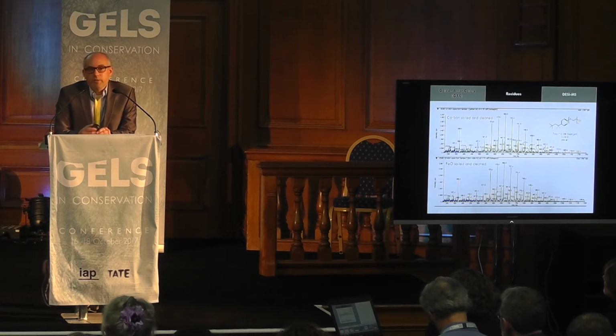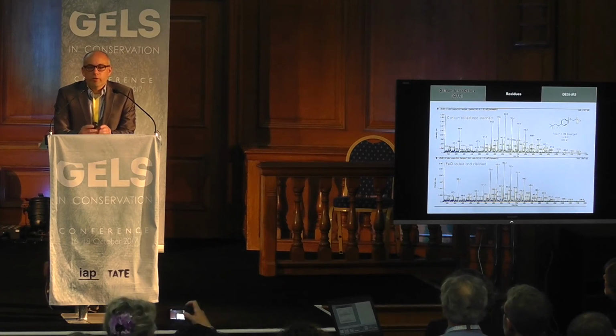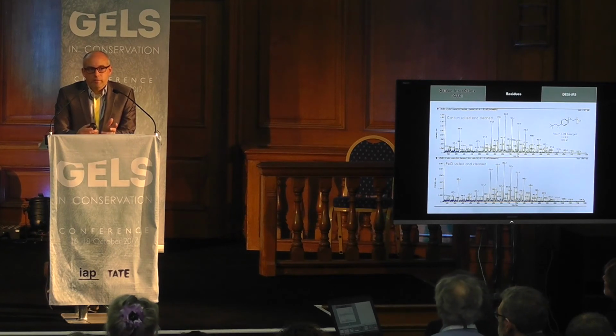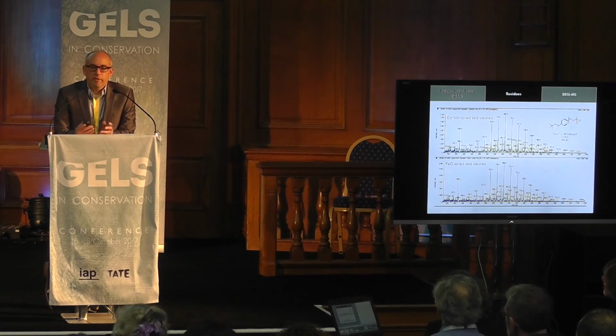Because I'm a mass spectrometrist, I do mass spectrometry on the surface of these paint films, and what we're going to see is that we do get the original gloss back that we started with after soiling, because surfactant does reaccumulate in these paint films. With just a few temperature or relative humidity cyclings, we can get that paint film to appear as it was before soiling. There isn't the presence of these siloxane solvents, so we can monitor that as well, much more sensitively by mass spectrometry.